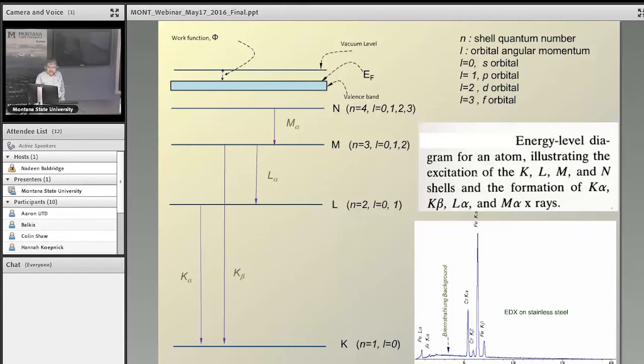So any electron that is ejected from the core level, say here in the K-shell, nature is very, very efficient. It doesn't sit in that configuration. It immediately adjusts within 10 to the minus 10 seconds and fills this hole. If this hole is filled by an L-shell electron, it's called a K-alpha X-ray. So you can see each element has K-alpha and K-beta X-rays, the iron K-alpha and the iron K-beta. That is because some of these holes are filled by the M-shell. So these are the K-beta. And similarly, chromium K-alpha, chromium K-beta.